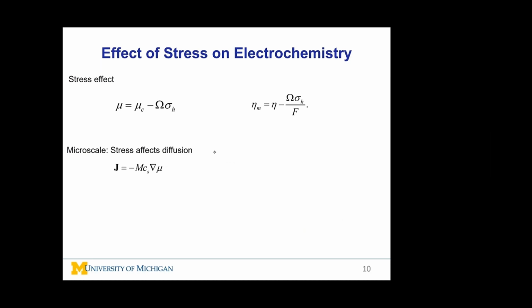At the microscale, stress affects lithium-ion diffusion in the solid particle through μ. During lithiation, lithium is under compression closer to the surface and under tension close to the center. The stress gradient on sigma H promotes lithium diffusion into the particle.